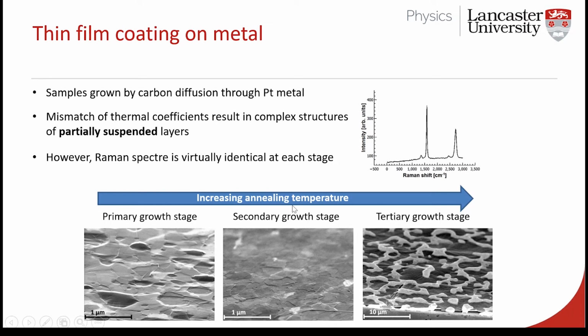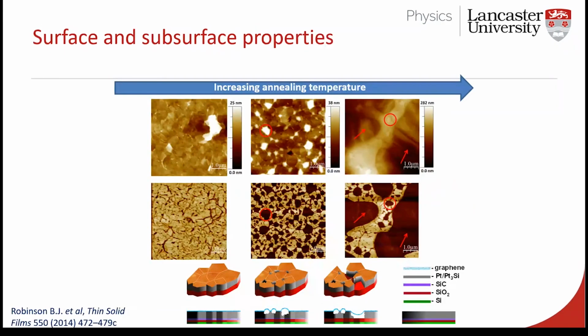And so depending on how they annealed their material, they got these different structures at the bottom here. And so the question that was posed to us basically was, what's going on? We can see the surface, we can see these weird structures, but what are they? You know, chemically, we know it's graphene. Chemically, we know it's just carbon. Chemically, it's right, but it should be flat. And this is where scanning probe microscopy really can come into its own. So we did a series of studies on this, and this is where now we take this multiparametric approach. So we scanned, using our microscopes, the surface of these materials.